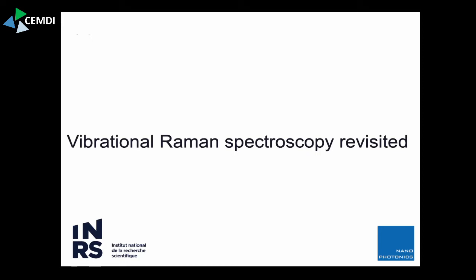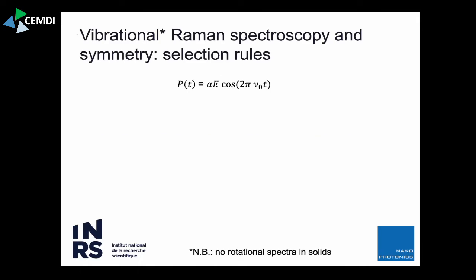So let me quickly revisit Raman spectroscopy. In principle, it's inelastic interaction of light with matter. And so you get the induced polarization, which is essentially the polarizability times the electric field. And we look at this as optical frequencies. So your nu zero would be your excitation frequency. Typically a laser, somewhere in the visible range. Now, what Raman suggested is what happens if your polarizability is not static? What happens if your polarizability oscillates with the vibration of the atomic or ionic species in your sample?